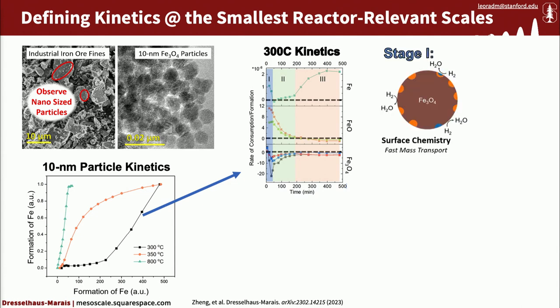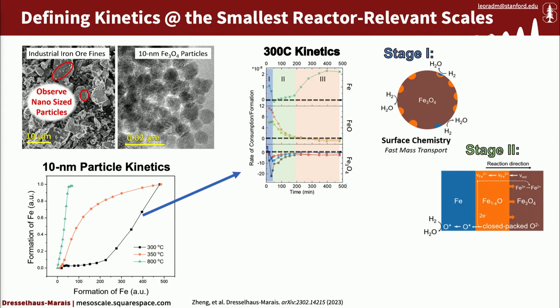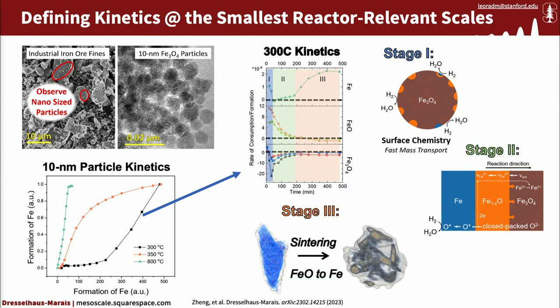The first of these stages is a really rapid surface chemistry, where all of the reactive sites on the surface are exposed, and therefore the kinetics go rapidly through every single step of the process. Then in stage two, we start to slow down because we passivated our surfaces, and now our kinetics are dominated by diffusion, or Fick's laws, as we discuss in materials science. And then in stage three, we end up in a very different stage of this process, where we've gone a large step of the way through the formation or consumption of the magnetite, and now we start to convert to iron.